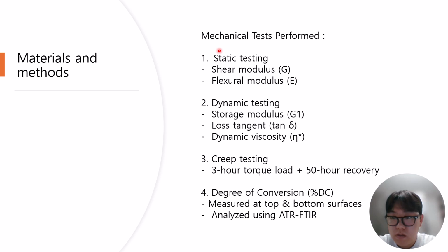4 tests were performed. First, static testing measured shear modulus G and flexural modulus E. Second, dynamic testing used sinusoidal forces to calculate storage modulus G', loss tangent, tan delta, and dynamic viscosity. Third, creep testing applied torque for 3 hours, then recorded recovery for 50 hours. Fourth, degree of conversion, %DC, measured at top and bottom surfaces using ATR-FTIR.